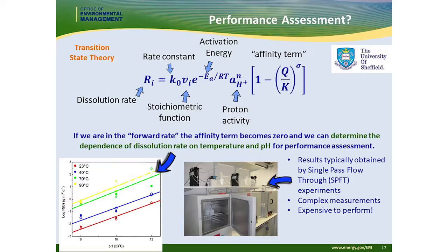As we were doing this, we tried higher temperatures as well before we settled in on the 3 that we're actually using. And what we find is that this is much simpler and easier to perform, and likely less expensive than the single pass flow-through test, which is typically what's used to get this similar type of information. So we feel like we can get more robust information, more field applicable information a lot more rapidly and economically.